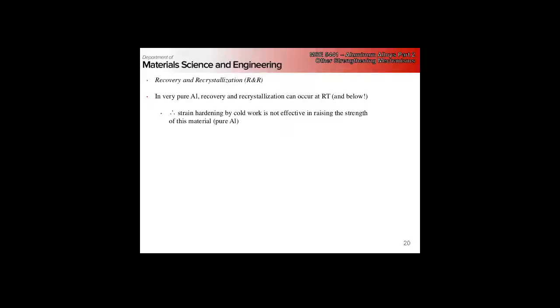So just as a refresher, what's the difference between recovery and recrystallization? Right? What's recovery? Annihilation of dislocations, but you're not changing your crystallographic structure. Right? And both recovery and recrystallization happen in 2 forms, static and dynamic. So static recovery is recovery that happens under purely thermal processing. Dynamic recovery happens under mechanical loads. So as you're deforming it, you're driving dislocations that are going to interact with each other and annihilate, right? So in terms of dynamic recovery, we have thermal and athermal effects, but that's sort of a sidebar.